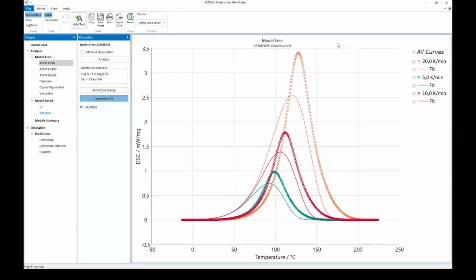I know that sometimes people calculate very fast according to single-point model-free kinetics, just take a maximum point, make an estimation of activation energy and think, yeah, it's a result. But you see, it's not a result. It's a very, very rough example result, and this result could not go to some publications, and in any case it cannot go to real industrial problems, where the results of kinetics must be very fine and calculated with less error.